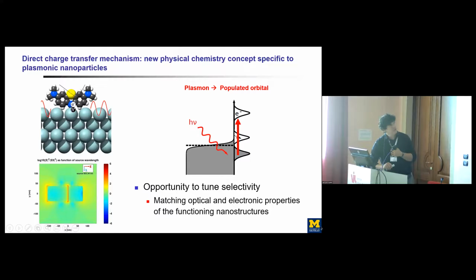And now the advantage, or the difference, between this mechanism and the other one that I proposed, the indirect one, would be that in this mechanism you actually would have an opportunity to tune selectivity, because simply by tuning the resonance here, you can skip these orbitals that are closer to the Fermi level, and potentially you can excite the orbitals that are further from the Fermi level and then drive chemistry to those orbitals via this resonant charge transfer, resonant excitation or optical excitation at this interface.